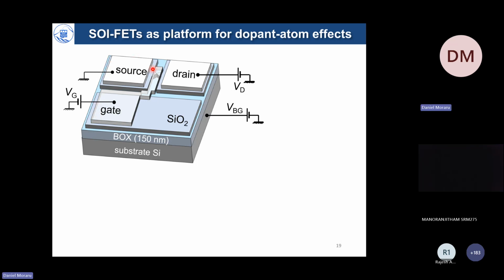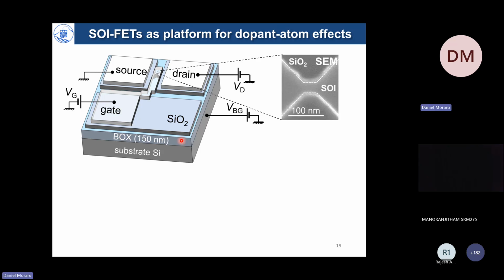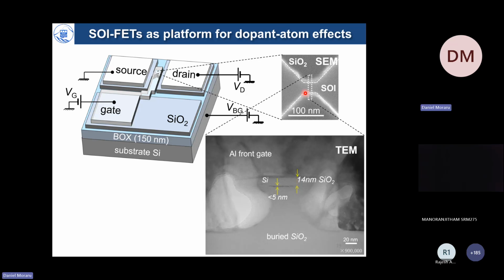You can see also the source, drain, and gate are covered by a metal, which is aluminum in our case, and this is also a typical biasing circuit. So what is important for our devices is that we have a very narrow and very short channel that can be developed thanks to our techniques of handling resists with electron beam lithography exposure. In terms of thickness, as shown by this TEM image, the channel can also be extremely thin, just a few nanometers or 10 nanometers with some degree of control.